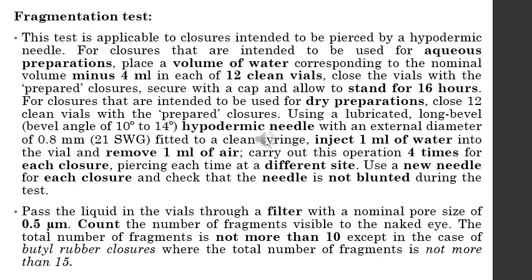Next test is a fragmentation test. Now this is applicable for closures which are intended to be pierced by a hypodermic needle. So there are two cases. Number one, we have an aqueous preparation. Number two, we have a dry powder or a dry preparation. Now in case of aqueous preparation, if the volume of the vial is 20 ml, for example, then we have to take 16 ml of water and we have to put it in the vial, close with the help of closure, and keep it aside for 16 hours.